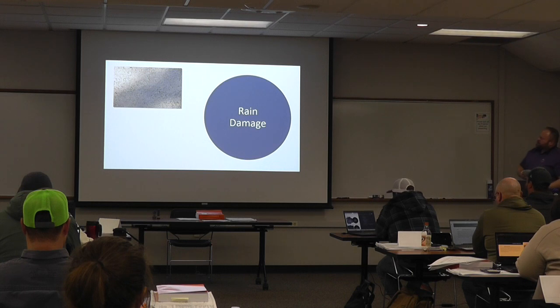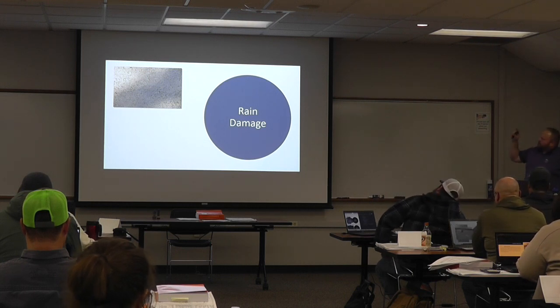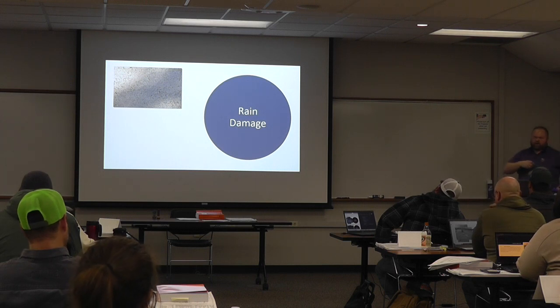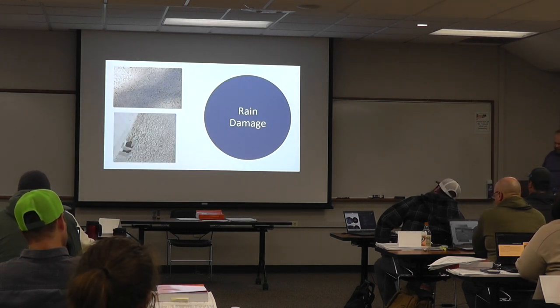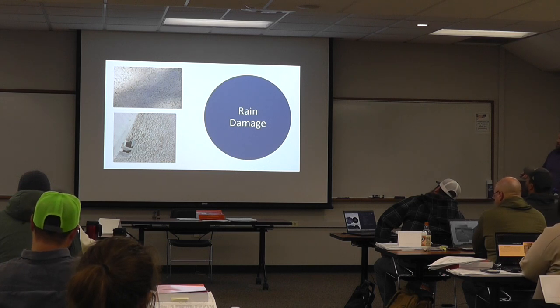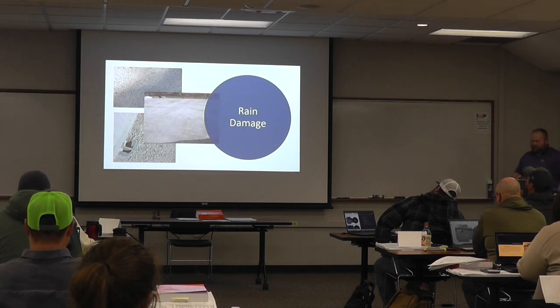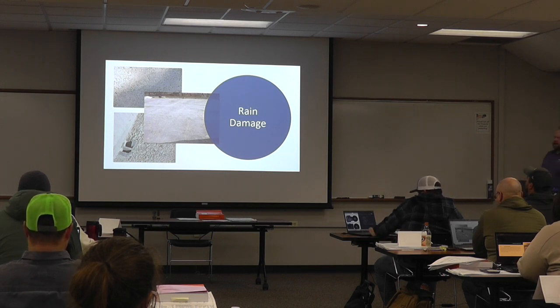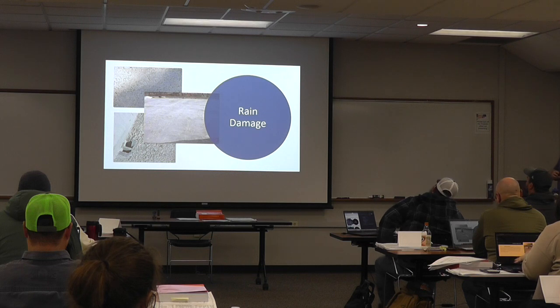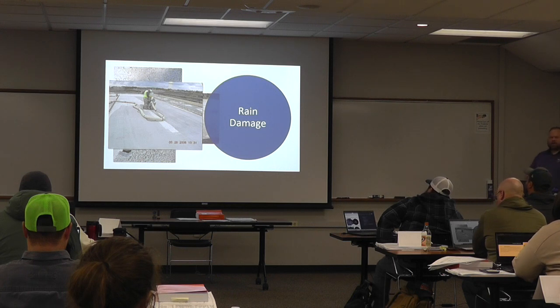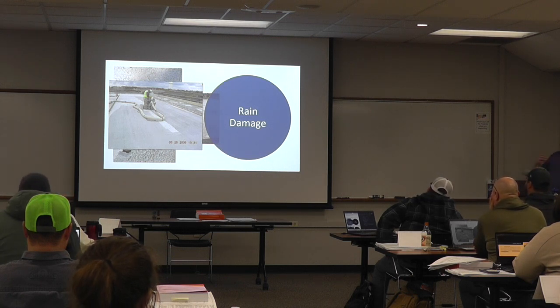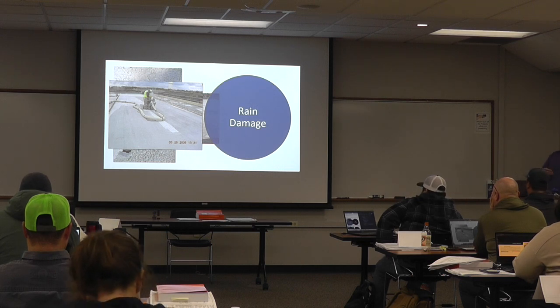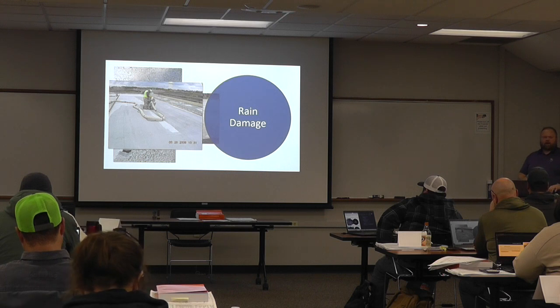Because what can happen, especially on a bridge deck, if it's raining, you're going to wash away the surface. Especially at these upper drain areas here, you can really see that coarse aggregate. You wash away all the paste from the surface. You can also run into issues being able to finish it right and get your texture on it right. The durability of the concrete is going to be in question, and it's a costly repair. Coming out to diamond grind is not cheap, and it's generally something the contractor probably pays for if they're pouring in the rain, but there are also schedule implications. There's going to be probably months of negotiation on who pays for what and when they're going to get out there, so we might as well just try to avoid it and protect it from getting rained on.